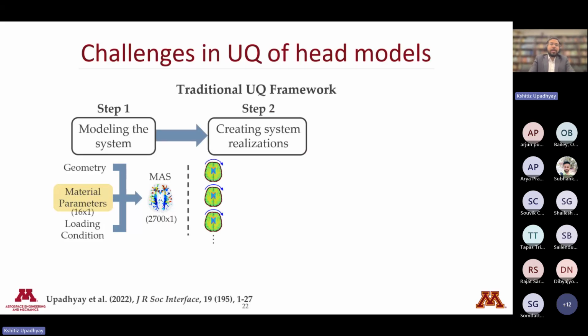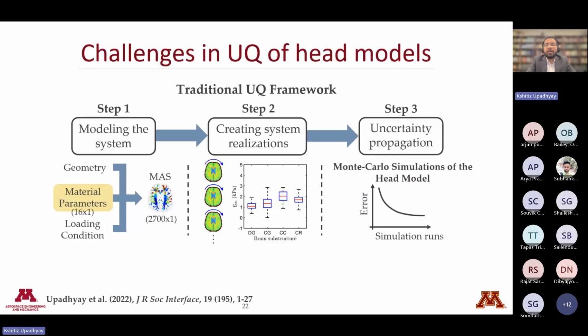Now, once we have the system, the second step in UQ is to create system realizations. Realizations just means copies of the computational model. So we have to somehow create copies of the head models with different sets of input parameters that are usually sampled from a probability distribution. Once we have these different realizations of the computational model, the last step is to propagate uncertainty by running simulations in a Monte Carlo fashion. So running many simulations, and eventually, when the simulations converge, calculating the uncertainty parameters such as standard deviation or coefficient of variation.